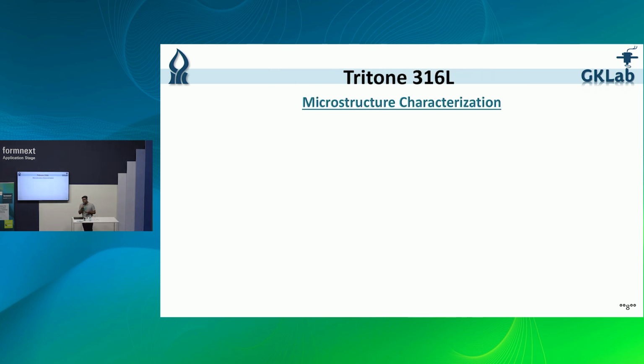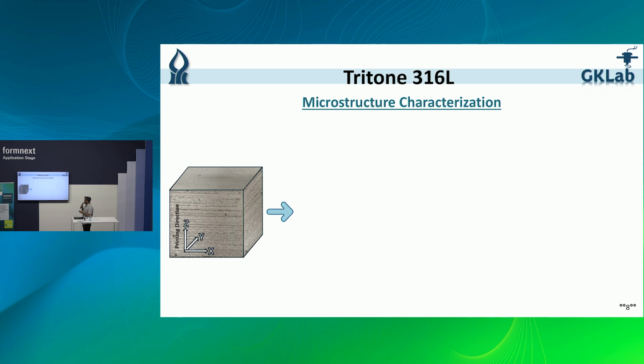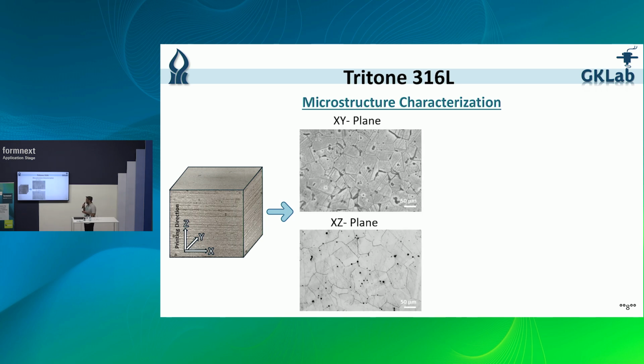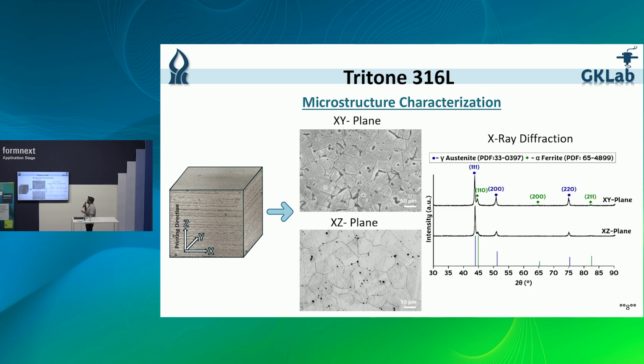The following results were obtained by the characterization of a 316L stainless steel alloy. The microstructural characterization included examination of both the XY and XZ planes of a printed cubic sample in order to examine whether there is dependency in the printing direction. Here we can see microscopic images of these planes that reveal the presence of a primary phase of an austenitic matrix and a secondary phase of ferrite. The presence of these phases is also indicated by an X-ray diffraction analysis of both planes.